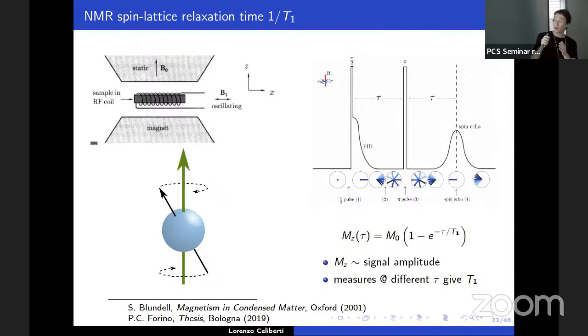The point is that when you flip the spins due to the perturbation, due to the interaction with the lattice, this tends to go back to the equilibrium value on the z-axis. The time that it takes to go back is called the spin relaxation time T1. To measure this, usually one reproduces these measurements at different times tau. In the simplest case, you have this kind of relation, and you can fit it to your experimental data and extract T1.